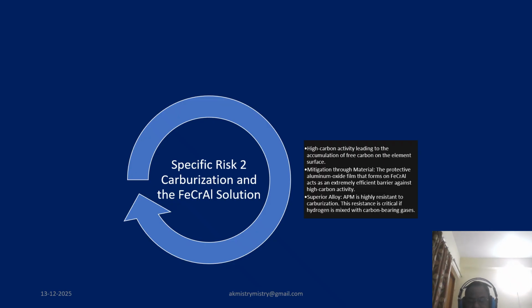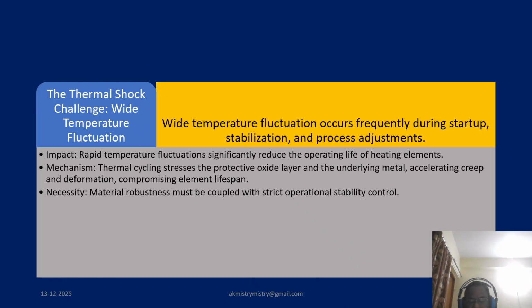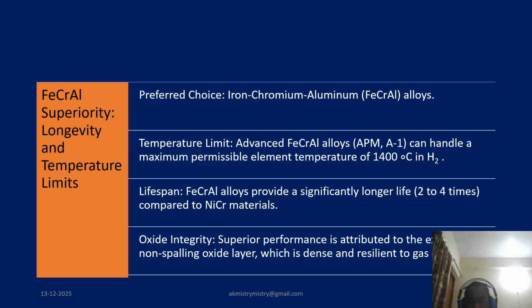Operational reliability includes wide temperature fluctuation, particularly during startup and process adjustment. This thermal shock is highly destructive. A rapid temperature fluctuation significantly reduces the operating life of heating elements. The mechanism is simple. The thermal cycling stresses the protective oxide layer and the underlying metal, accelerating creep and deformation both. So this means material robustness alone is not enough. A strict operational stability control is absolutely necessary.